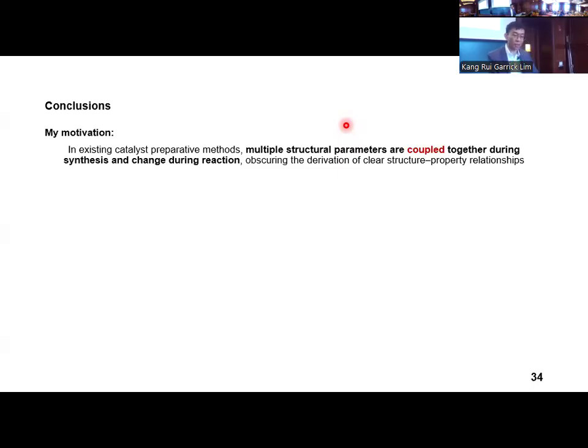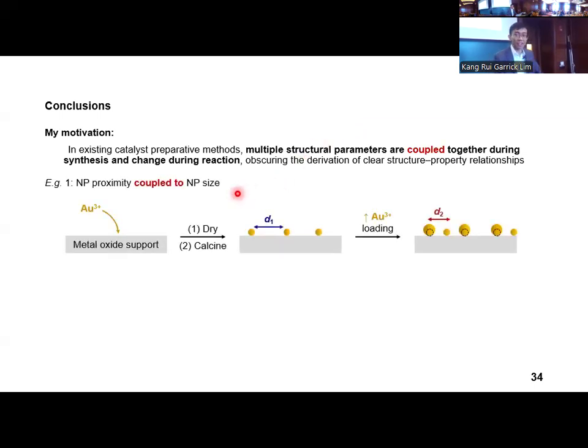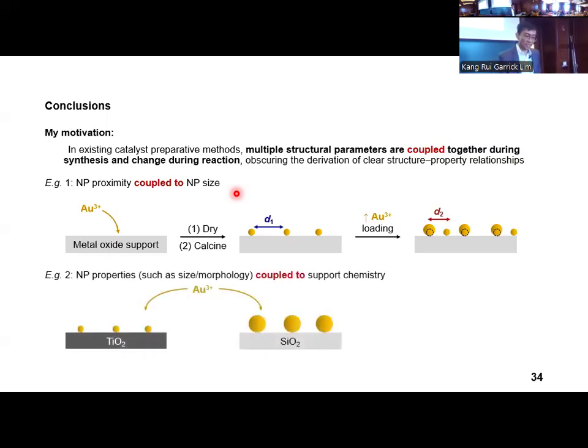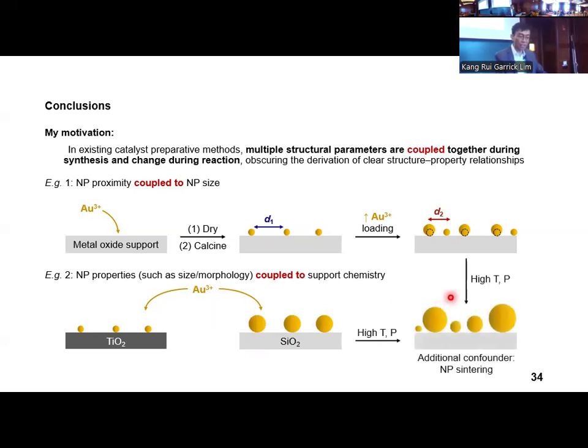Consequently, the strong coupling of structural parameters obscures the derivation of clear structure property relationships to guide our future catalyst design. I exemplify my motivation with two examples. In the first half of my talk, I explained why nanoparticle proximity and nanoparticle size are coupled together and cannot be independently varied from each other during synthesis. In the second half of my talk, I described how the support chemistry strongly influences the nanoparticle nucleation characteristics and thus precludes independent variation to isolate effects arising solely from nanoparticle support interactions. Moreover, under thermocatalytic conditions of high temperature, pressure, and mechanical agitation, these impregnated catalysts are prone to nanoparticle leaching and sintering, which further confounds our catalytic analysis.